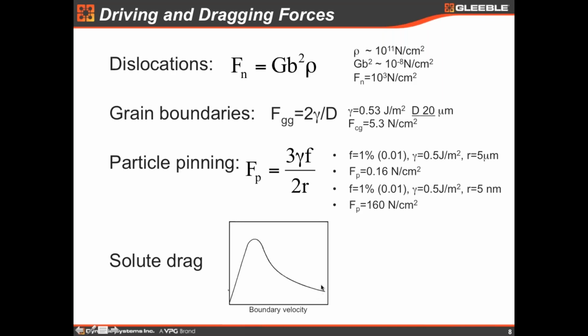On the other hand, at very high velocities, let's say dynamic recrystallization, that happens at very high speed, the grain boundaries almost ignore the solute atoms in the grain boundary. And I think the highest effect is on static recrystallization. So this is the peak. Of course, there's a very complex formulation for that. I have many papers. If you guys are interested, let me know. I can mail you the classic papers on solute drag. So let's cover it like that. Well, let's stop here for now.